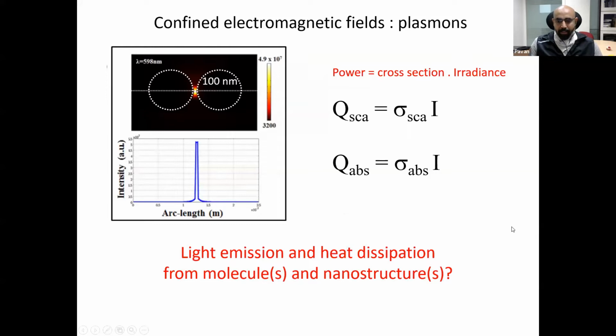Now, an important question to ask is, what happens to light emission and heat dissipation from molecules or nanostructures which are confined to such gaps? These gaps which you are visualizing are also in essence called gap-plasmons, because you are creating a very localized optical field because of the plasmons in the gap between two nanostructures. Now, this gap need not be only between a sphere and a sphere. This gap can also be between a sphere and, let's say, a plate, or a two-dimensional surface. So there is a gap between a particle and a film, and that too facilitates a very similar kind of electromagnetic field, but with some very different behavior of the dynamics of plasmons. So as we progress, we will see what kind of dynamics you will expect in such situations.